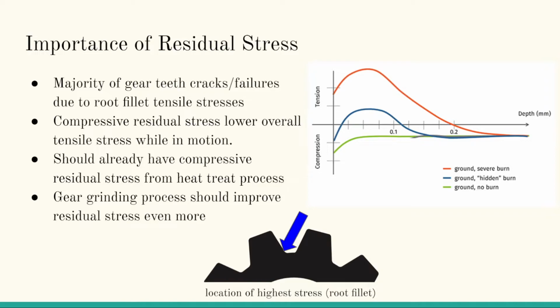The other important part of our project is residual stress, specifically the ones that are inside of the gears. The majority of gear teeth cracks and failures are due to root fillet tensile stresses. Compressive residual stresses lower that overall tensile stress when the gear is being utilized. Essentially, you increase the amount of compressive stress that is in the gear already. You also increase the amount of tensile stress that can be applied to the gear without failure.